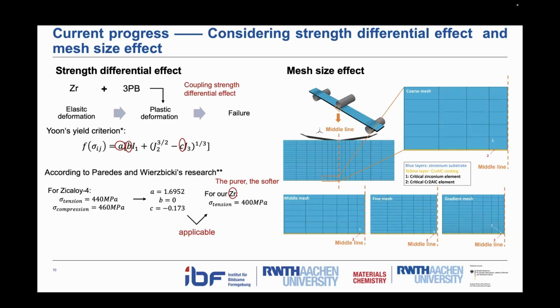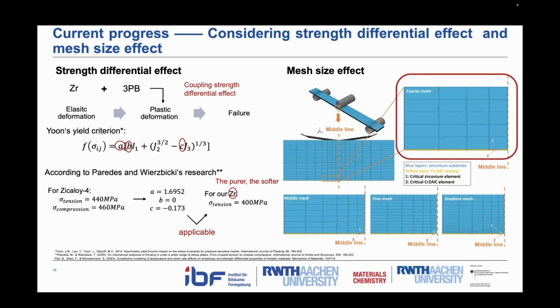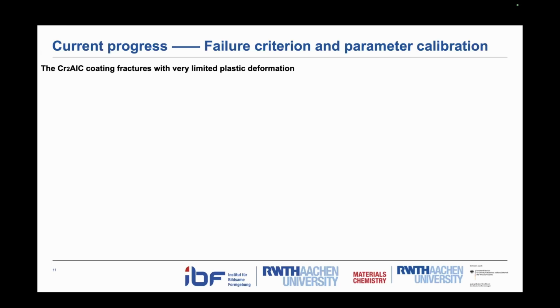So we run the simulations without coupling any failure criterion yet. And what we have found is that when the coating fractures, it fractures with very limited plastic deformation. And considering the data scattering, we finally adopted the maximum principal stress criterion combined with the Weibull distribution.